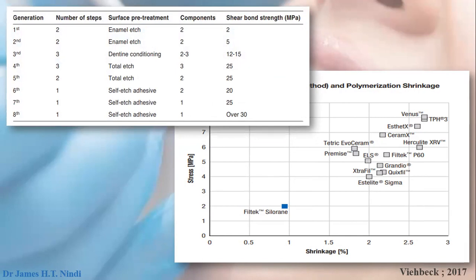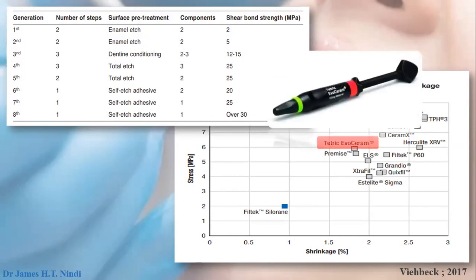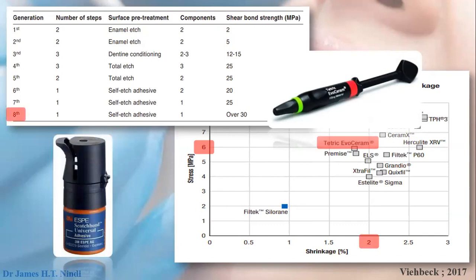Now, for this to be clear, I'm going to use a common example which you probably use on a daily basis. Let's say we take a common composite on the market, which is Tetric EvoCeram, which is there on the diagram. When you place Tetric EvoCeram in a cavity prep, and when you cure it, it will shrink, the volume of that composite will shrink by 2%. And that shrinkage will generate a stress of 6 megapascals. So let's say underneath this composite, you've used a universal adhesive, which is Scotchbond Universal, a common one on the market today. If you use this adhesive, the shear bond strength that it will offer is over 30 megapascals.